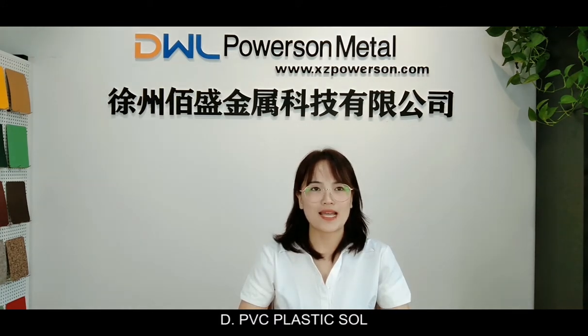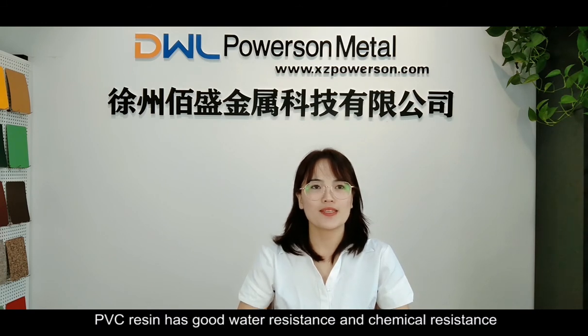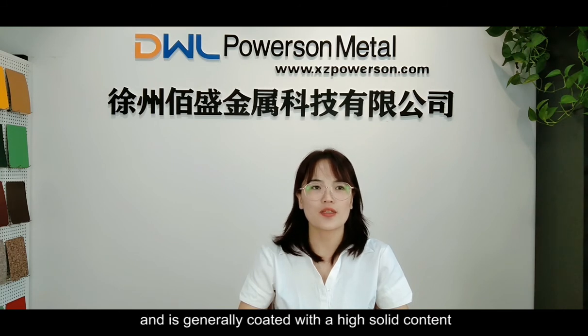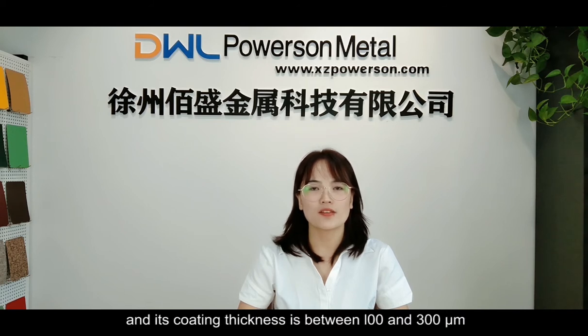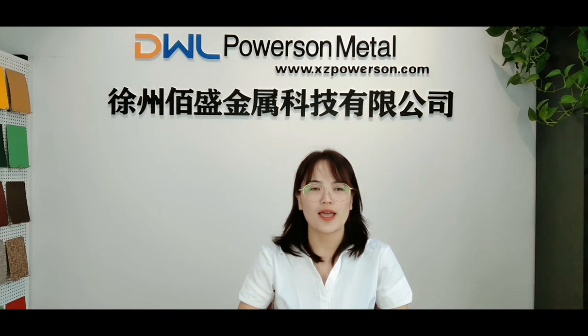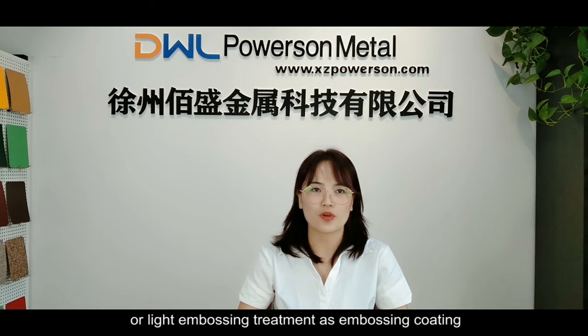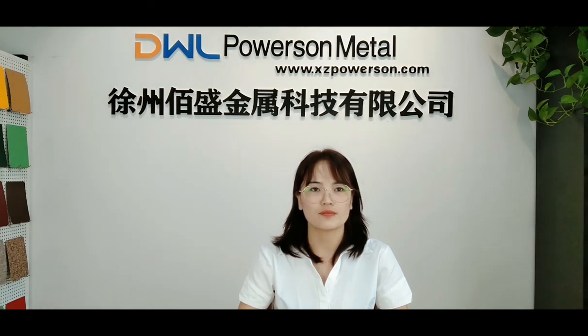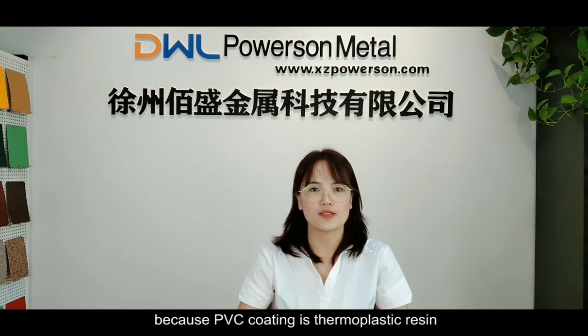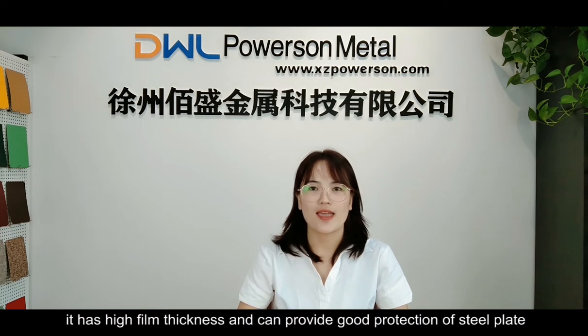D. PVC plastisol. PVC resin has good water resistance and chemical resistance, and is generally coated with a high solid content, and its coating thickness is between 100 and 300 microns. It can provide a smooth PVC coating or light embossing treatment as an embossing coating. Because the PVC coating is a thermoplastic resin, it has high film thickness and can provide good protection of the steel plate.